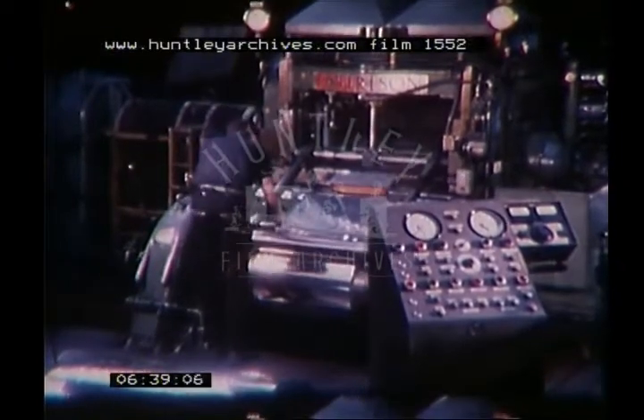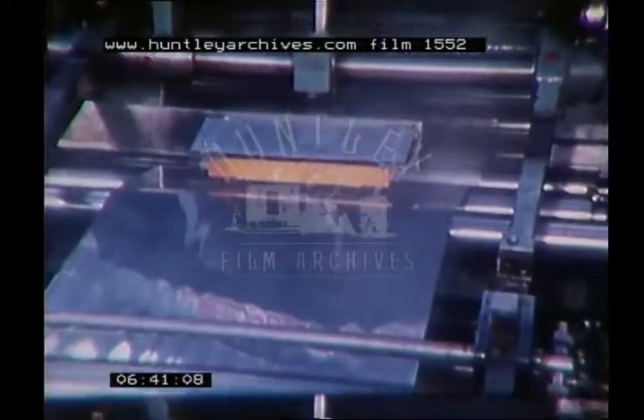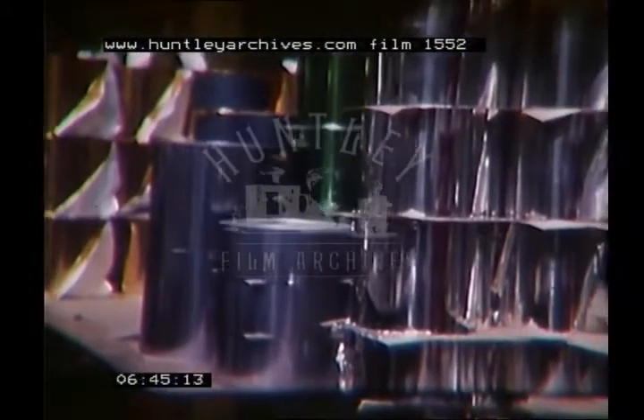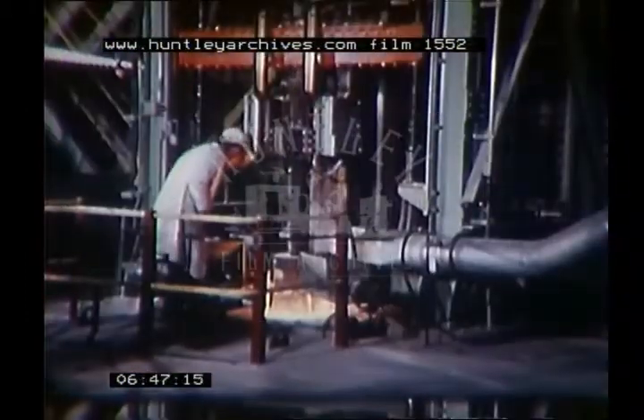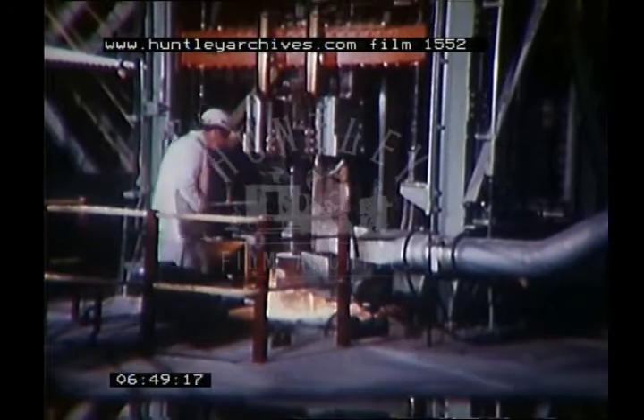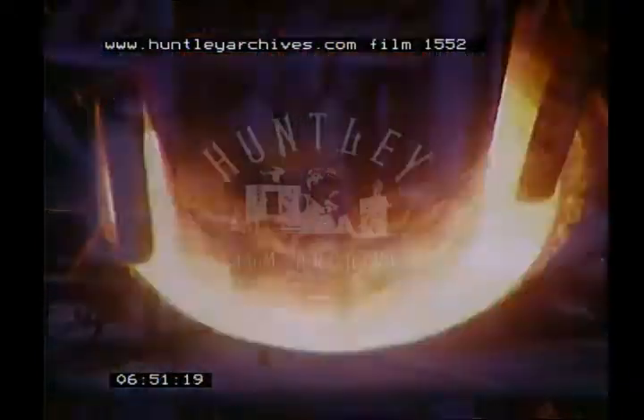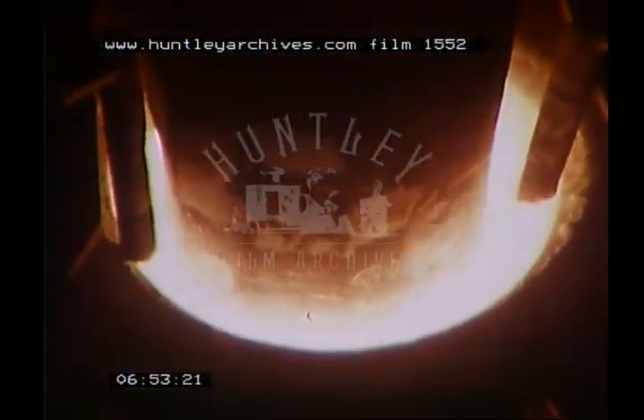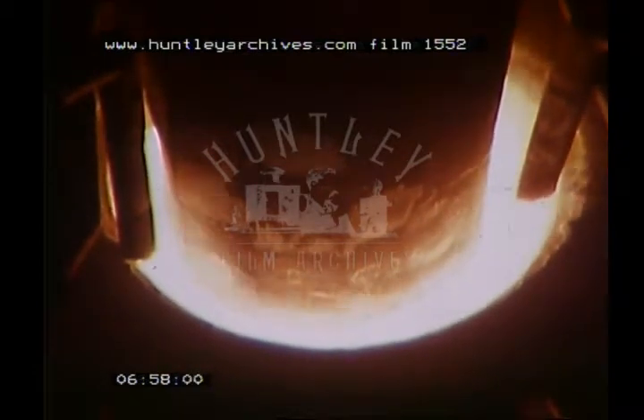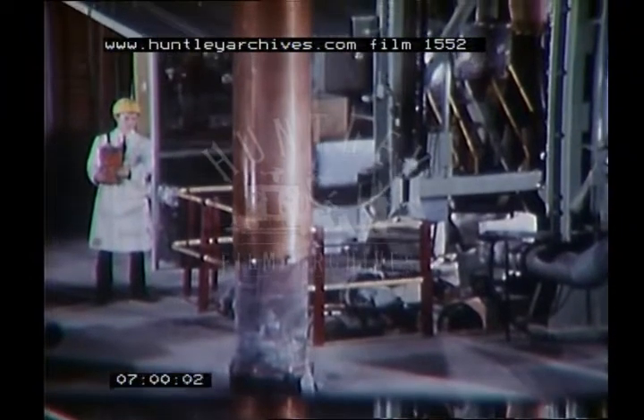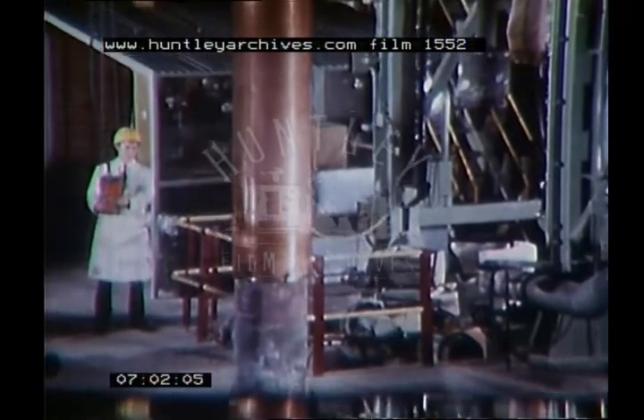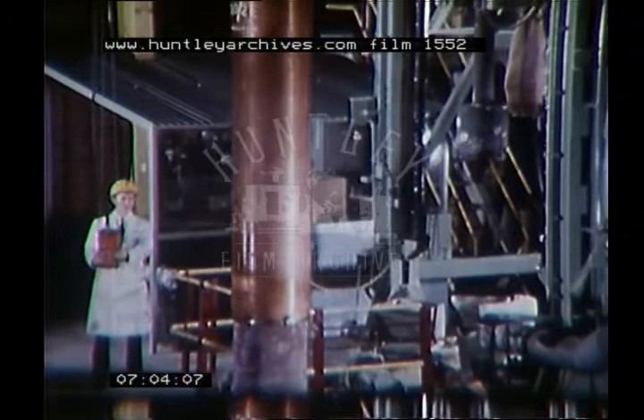To make steel free from inclusions, the new double melting processes have to be utilized. In the electro-slag process, steel is remelted through a fluid slag which absorbs or disperses the non-metallic particles in the steel. The atmosphere is excluded throughout the operation, and the final product is very high-quality material, containing only very small, widely dispersed inclusions.